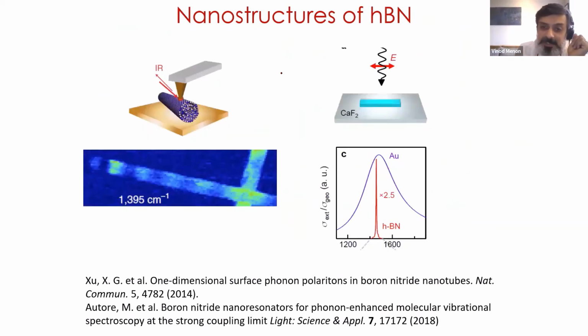People have made resonators, and you can see here compared to a gold resonator, the hBN resonator in the mid infrared has a much higher Q value, which is a good sign, especially if you want to couple these to molecular vibrations and so on.